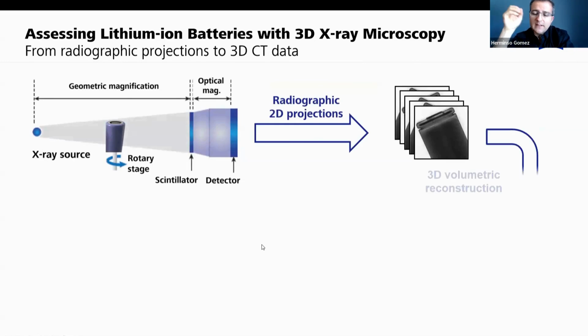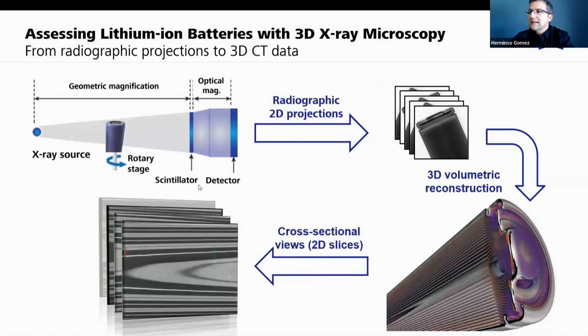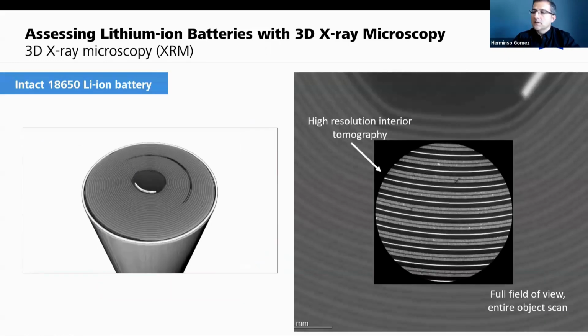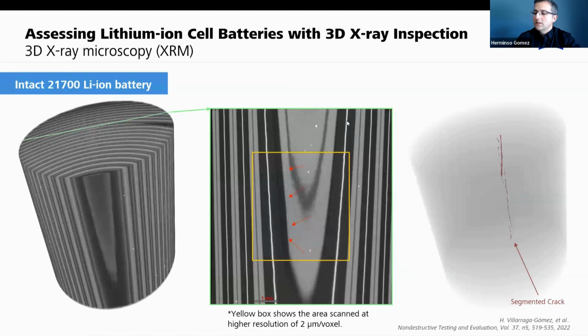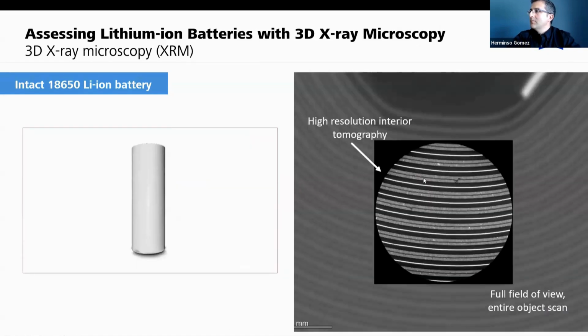The workflow, if we think now in X-ray microscopy, what allows you to see at high resolution is the ability to add a detector that has a scintillator and an optical magnification that is going to magnify the X-rays after they are converted into light, to give you the ability to see a 3D reconstruction at high resolution. When I'm talking high resolution, it's because you will be able to see some high density particles that are very small, and cracks in a cylindrical cell. And this is potentially something that you won't see if you try to use just a single flat panel detector in a micro CT. So this is why it's important to use optical magnification with the 3D X-ray microscopes.